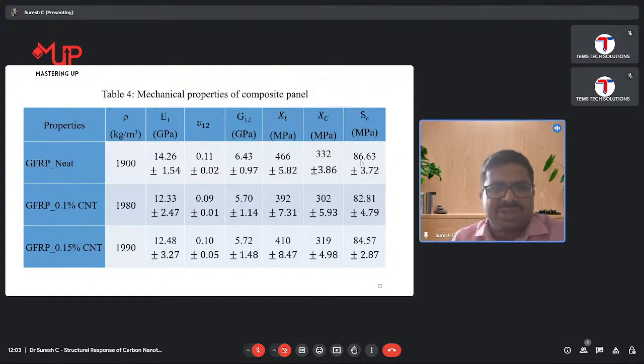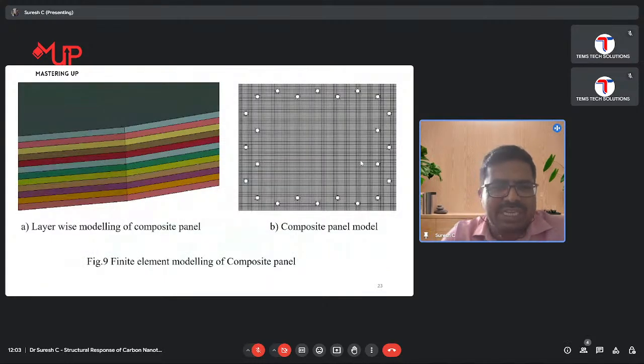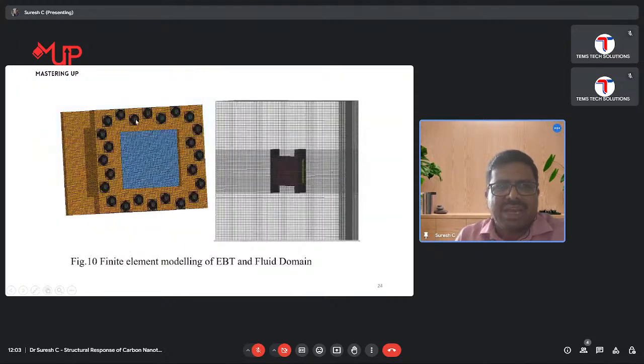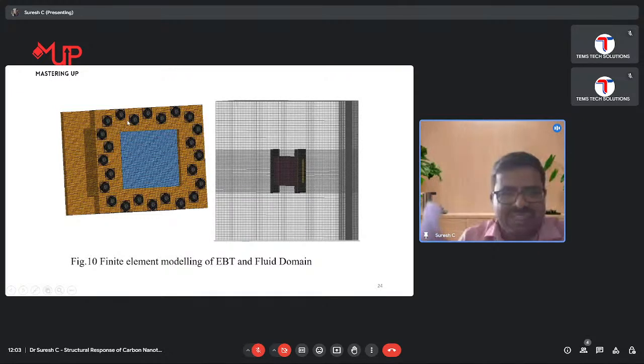These properties are used to carry out the numerical simulations using LS-DYNA software. In LS-DYNA, this is the complete composite test plate which we have fabricated. From the side, if you see, we have fabricated with a number of layers based upon how much thickness we need, so we can increase the number of layers. Layer-wise modeling is also shown, and if you see from the front, it will look like a beam. That is the composite panel model, and it is meshed using finite element software. And we have modeled the whole EBT fixture, that is the explosive bulge test fixture, with the bolts and nuts, everything as in the real case.